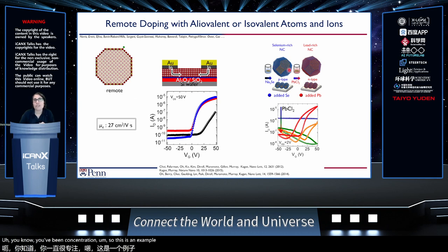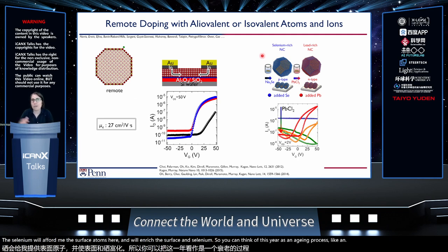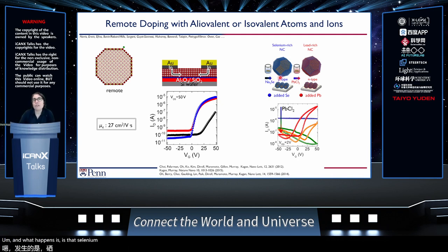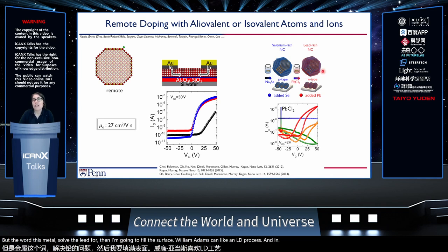This is an example in lead selenide, which is one of the ones we had done this work in earlier. If we have an ensemble and treat it with a metal salt or a metal chalcogenide, in this case sodium selenide, the selenium will coordinate the surface atoms and enrich the surface in selenium. You can think of this as an ALD-like process: if there are metals on the surface, the selenium will attach. Selenium is a low-lying acceptor in lead selenide, so it is an effective p-dopant in the material. Then if you take the same material and immerse it in lead chloride, this metal salt, the lead will bind to the surface selenium atoms, again like an ALD process, and enrich it in lead. And lead is a low-lying donor in lead selenide. So what does that mean?